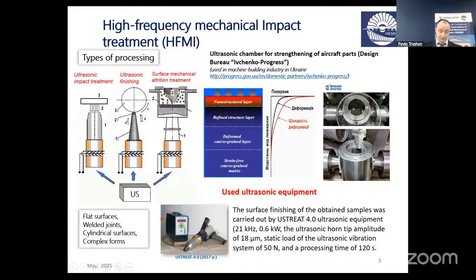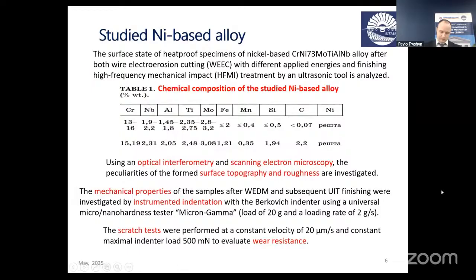In this study, we used the ultrasonic treatment, portable one, and its parameters and the regime is shown in this slide. The chemical composition of the studied nickel-based alloy is shown on this slide. We used optical interferometry and scanning electron microscopy to investigate surface topography and roughness of the samples. Mechanical properties were assessed by instrumented indentation technique, and the wear resistance was evaluated using repeated scratch tests.